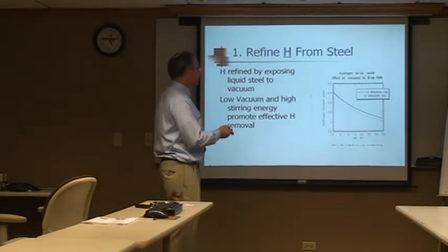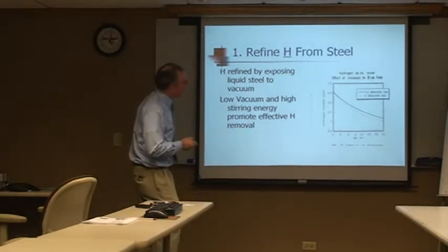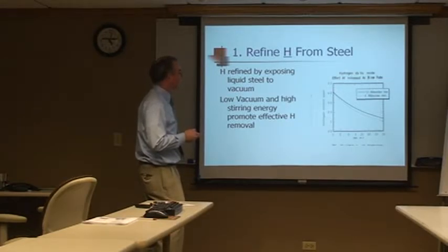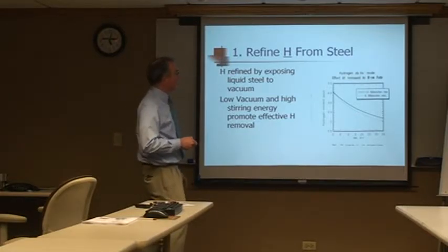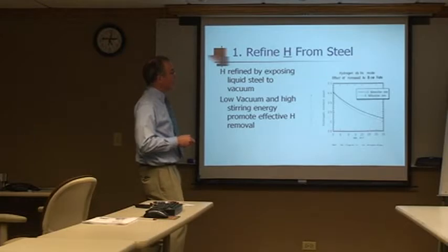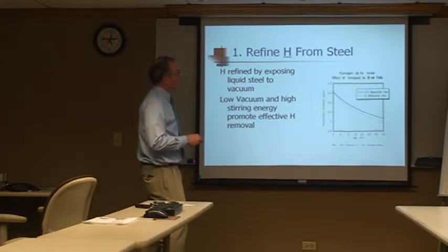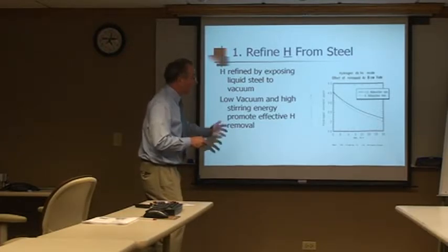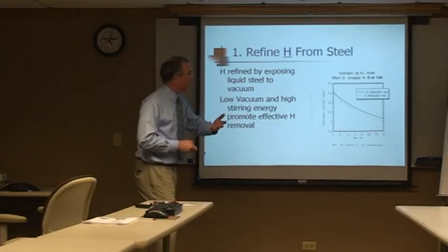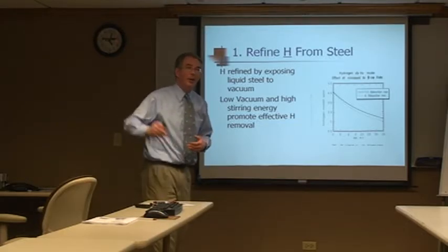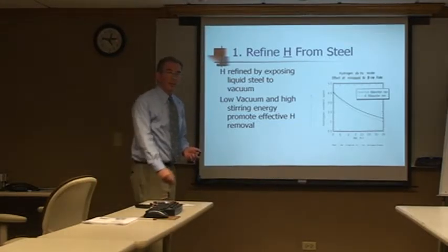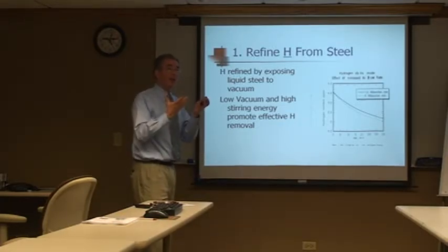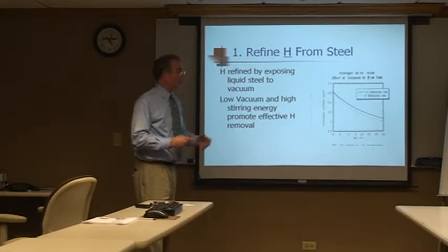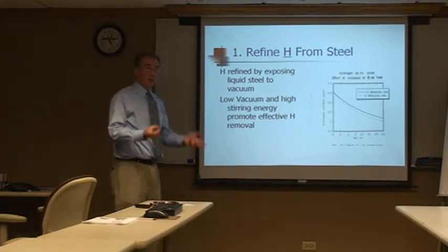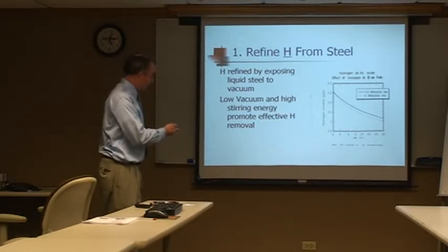So if you look, just as a difference here, you see this dotted line and you see this solid line. This is kind of giving you an idea and difference in stirring energy. So say this solid line is in argon only. This dotted line is showing you what might happen with the combined stirring energy of induction stirring and argon bubbling. Being able to refine more hydrogen, use that vacuum. Dan had a good analogy with the little fine particles. The more steel we can expose to the vacuum, the better job we're going to do refining it. And that's where the stirring energy comes in, having a stronger vacuum to remove those particles.